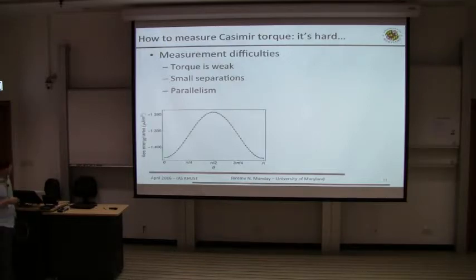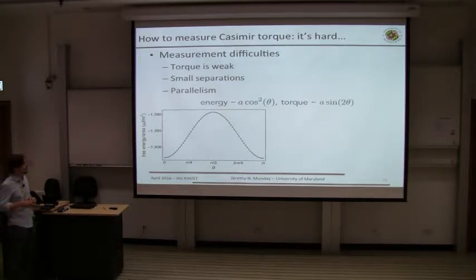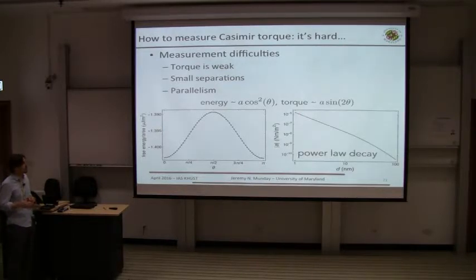So also we can look at the free energy per unit area. This is the way it would vary as a function of angle. And you can see there's a relatively small variation here. This is microjoules per meter squared. So you want to take a derivative of this and look at the torque, and you get something like this. Now we're looking at something more on the nanonewton meters per meter squared values here. And there's a power law decay here as well. So you're thinking maybe tens of nanometers as ranges you might want to try to measure this.